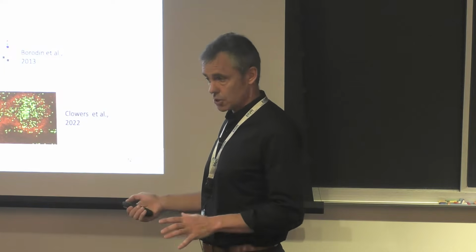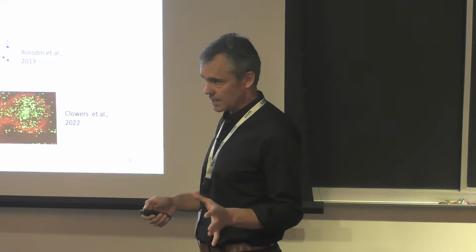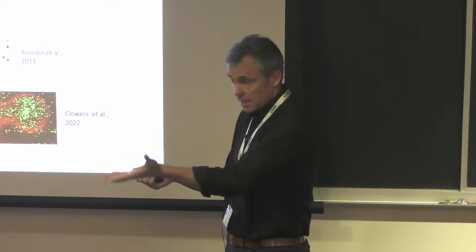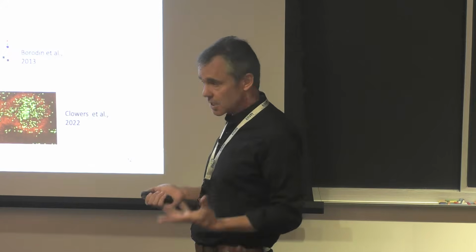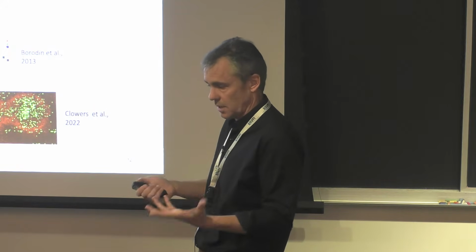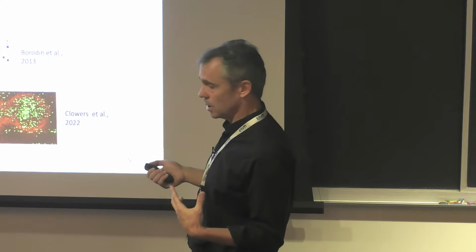We can control the microstructure in ways that will prevent swelling. The moment you put helium in there, it's unavoidable. It's physically unavoidable, because the helium is, like I said, very large and produced in large quantities.